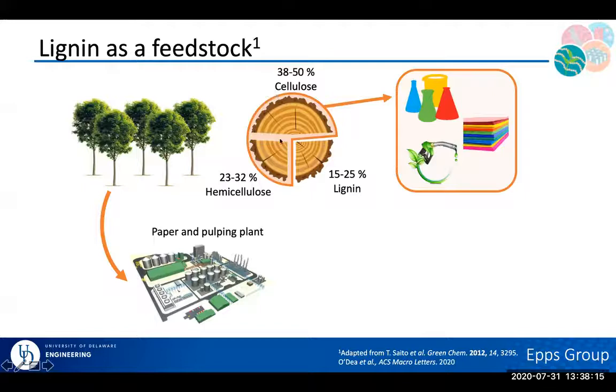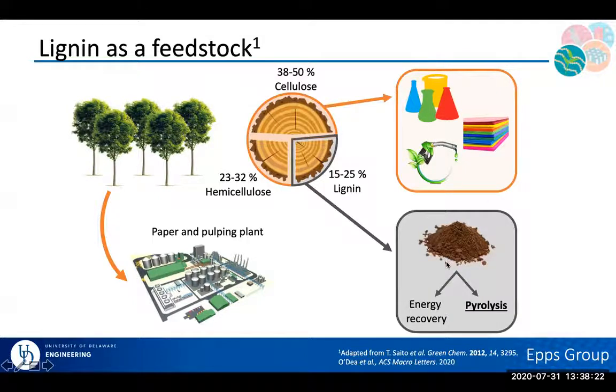So I can take the cellulose and hemicellulose, as I described earlier, and use that for a variety of things. But the lignin is essentially burned for energy recovery or thrown away in the landfill. And our goal here is, can we actually use that to make commercially viable products? Why do we want to do this? Because if I think about the economic viability of biorefineries, one of the key challenges is that if I'm taking about 15 to 25% of my starting material and throwing it away right off the bat, that doesn't really help the economics of my process.